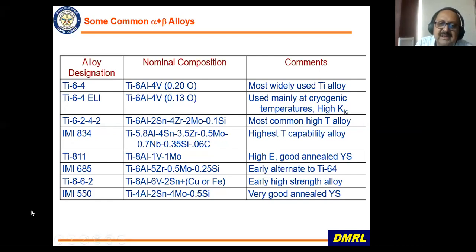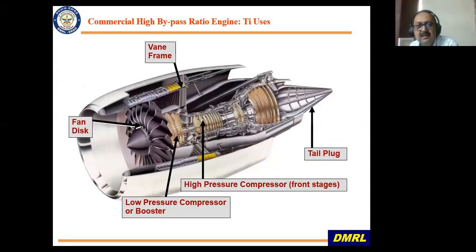And most of the high temperature titanium alloys, as you can see, will have silicon. I will show you what silicon does. It improves basically the creep properties. So here are some examples of commercial alpha plus beta alloys and also near alpha alloys, which is a subcategory of alpha plus beta alloys, which occurs towards the alpha phase region.